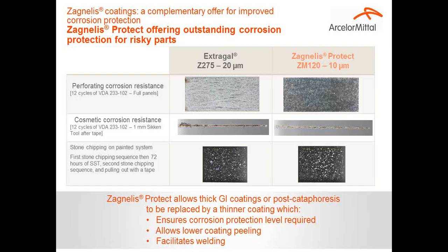So with replacement of thick GI coating by Zagnelis Protect 10 microns, we ensure the protection against corrosion, but we also have lower coating peeling. We are decreasing the thickness of the coating, so we have lower peeling, and the welding is easier because of the thinner coating.